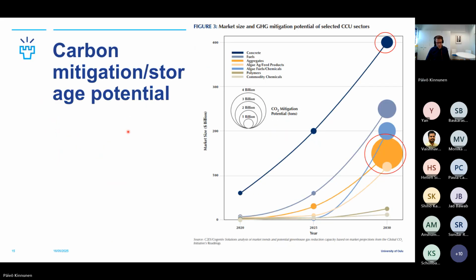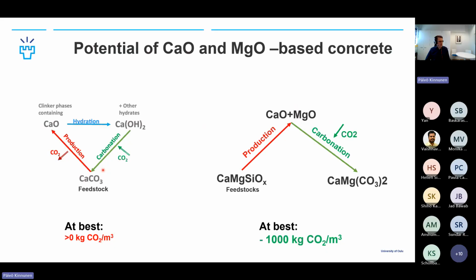So here, pretty much the same thing, just to reiterate: in the current paradigm, what we have as the feedstock is calcium carbonate. We produce calcium oxide or clinker phases containing calcium oxide, and then we emit CO2. And then in the reaction, what happens is the hydration, giving calcium as portlandite and other hydrates. And then you can, in theory, carbonate that, and this is what's done, for example, in demolition waste carbonation. You can take some of the CO2 back, and at best you can have zero CO2 here, and actually, because you're not carbonating all of the calcium, it's quite much less.